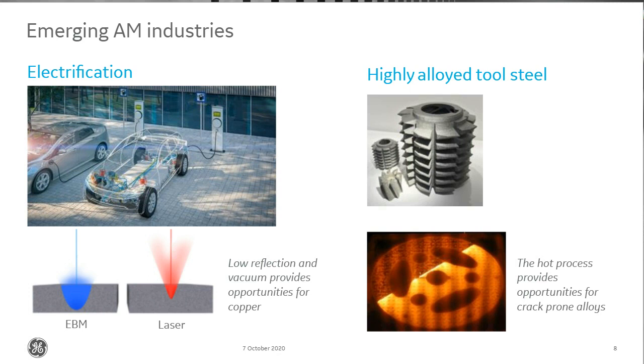So this is kind of similar to the case we discussed earlier with the titanium aluminide. These high alloyed steels are extremely crack prone, and by manufacturing them at a very high elevated temperature, we can melt the material with what's referred to as a small thermal delta. So basically, you can say across your component, you will have a very small thermal difference, and that means that you don't have any thermal-induced tension in the material.